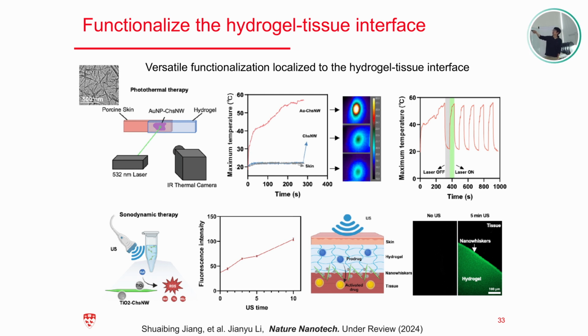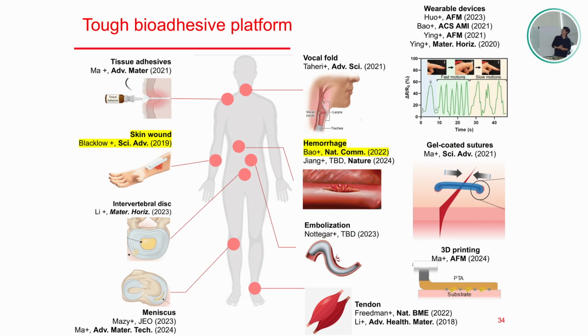We can decorate it with a gold nanoparticle for the photothermal effect, and that is only localized at the interface, and we checked the back of the tissue, which didn't get heated up. And then further we can combine with titanium oxide nanoparticles, which enable the production of ROS. There are some therapeutic functions. So that finishes the second part, and for the last part I would like to show you the applications.